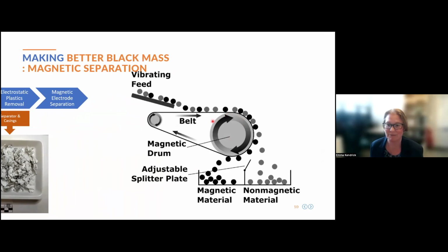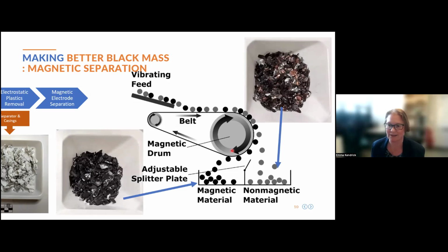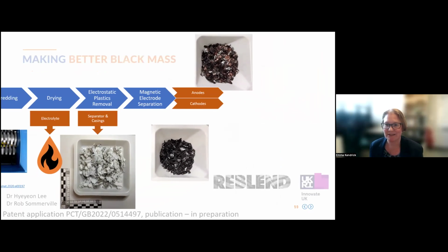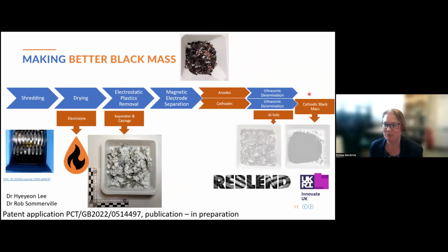And here we use a rare earth magnet on a belt, and we can exploit the active material properties to separate out magnetic materials from the non-magnetic materials. What we do here, because the cathode materials tend to be paramagnetic, we can actually use that. And as long as they're stuck to the current collector, we can separate out the aluminium coated parts and the copper coated parts of the electrodes. So here's just some examples of the aluminium coated, which have been separated because we've exploited, in this case, the NMC properties. And here the graphite, which is non-paramagnetic, which is stuck to the current collector, can be separated out as a non-magnetic material. So we need to take it from these kind of large pieces of coating to then produce powder.